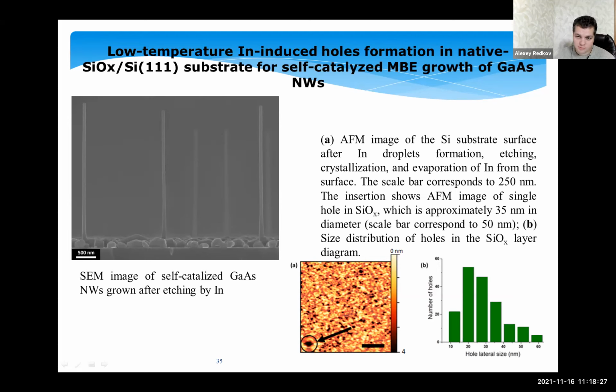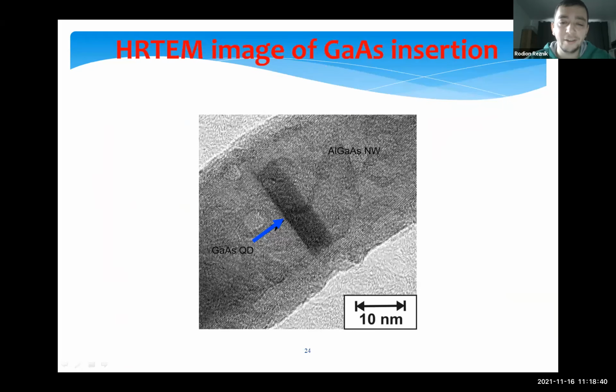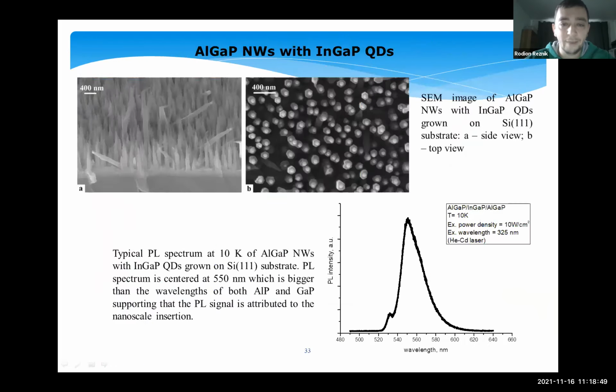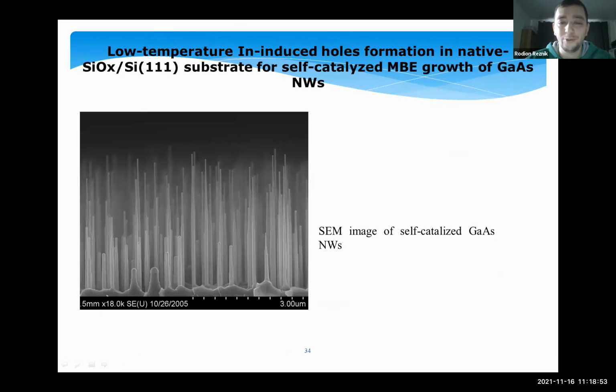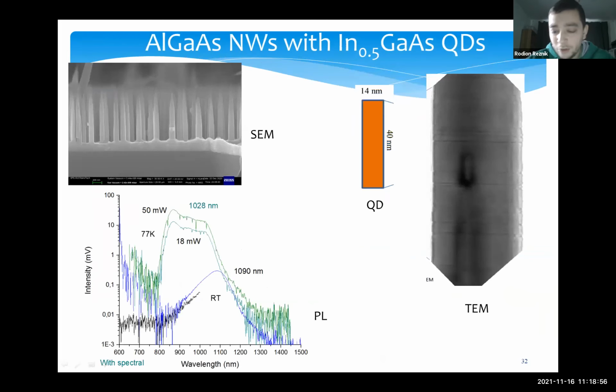Thank you for this good question. First of all, in case of aluminum gallium arsenide and gallium arsenide material system, there is no stress between these two materials. But in case we add indium to the solid solution of the quantum dots, of course we have stress. And with increasing indium content, the stress increases too. So you can see on this TEM image, this stress black field. So of course it can affect the quality of quantum dot, but hopefully because of the small size, we will not have this effect.